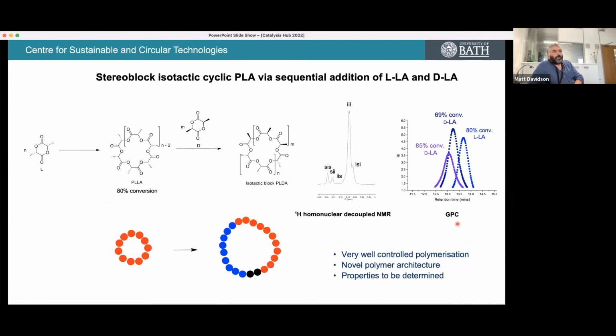So we thought we'd really push the control that we were getting with this ring expansion polymerization. One of the things that, again, we've done with linear polymers in the past using a co-initiator, we've done similar experiments. But I'll just take you through this experiment. What Philip's done here is he's taken the L-lactide and catalyzed the ring expansion polymerization to the cyclic PLLA to around about 80% conversion.